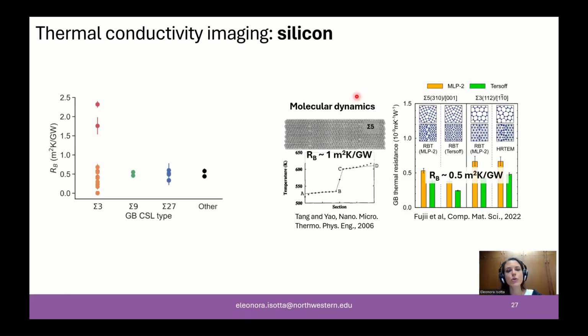Okay, so now we can draw some overall conclusions on what we saw. The differences that we were seeing for the sigma 3 boundaries are rooted in distinct morphological variations of this boundary. In fact, we can see that a smooth sigma 3 offers a resistance that is basically 0, whereas whenever we introduce roughness, this value seems to increase to the neighborhood of 0.5.